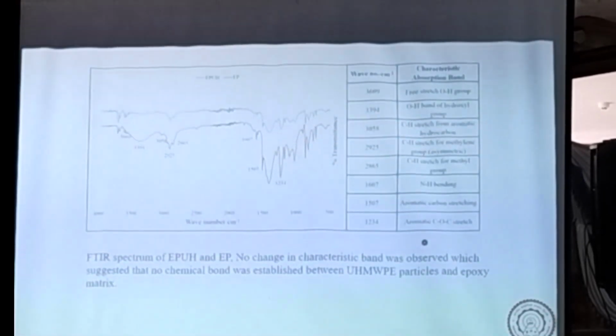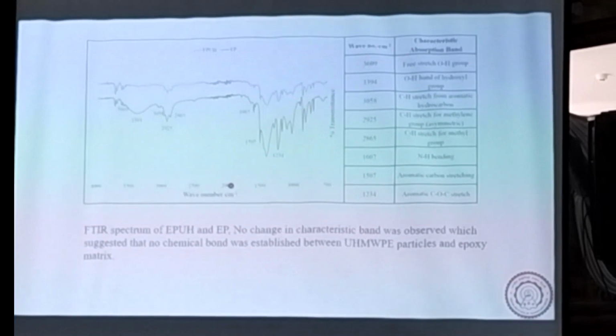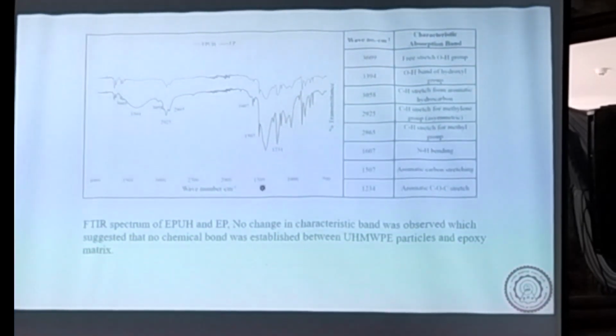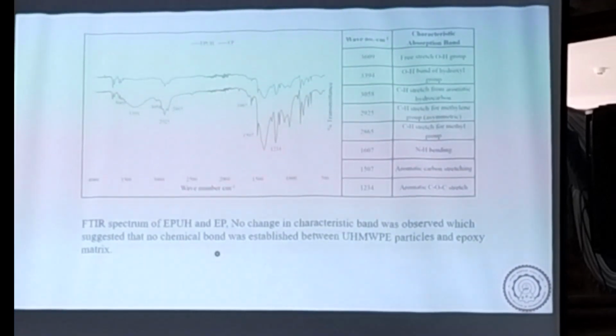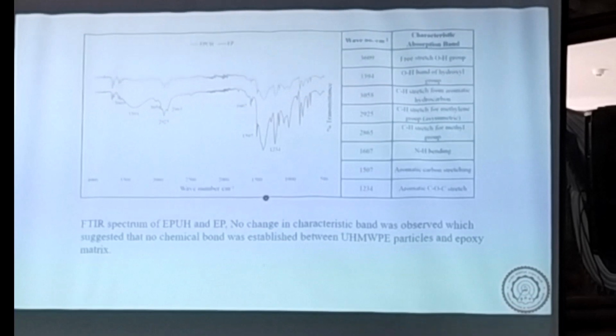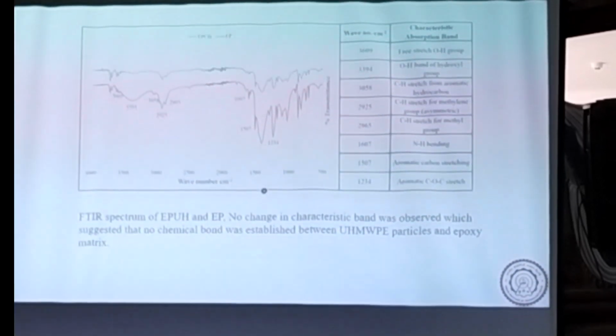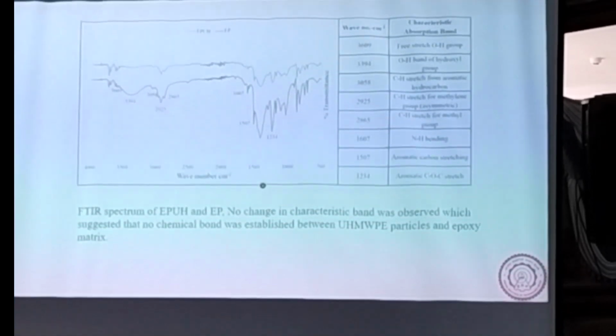Another important thing is about the bonding between the UHMWPE particle and the matrix. Matrix is SU8. We find that there was no chemical change, so there is no chemical bonding. The bonding is basically physical in nature. The UHMWPE particles basically get covered by the cross-linked epoxy.